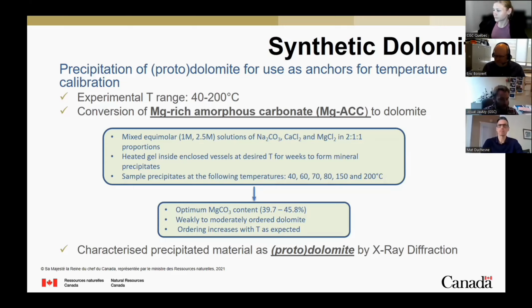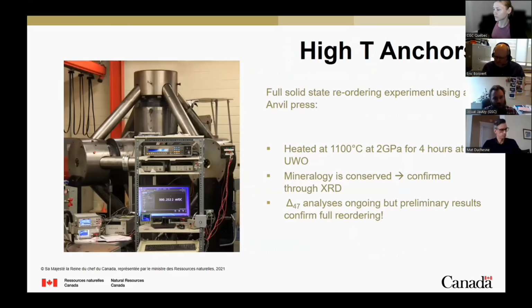For the very high temperature anchors, we are taking advantage of a phenomenon that happens to the clumped isotope distribution in a carbonate crystal. When you heat them above a certain temperature, you start to diffuse the heavy isotopes apart from each other, breaking those clumps of heavy isotopes. If you heat it for a long enough period of time and at high temperature, you will go to a stochastic distribution, a totally random distribution of your heavy isotopes in the crystal lattice. That creates a very high temperature anchor. The problem is that if you heat it to 1,000 degrees Celsius, which is what is necessary, you're going to just disintegrate your carbonate. You're going to decarbonate it. So you need a very high confining pressure.